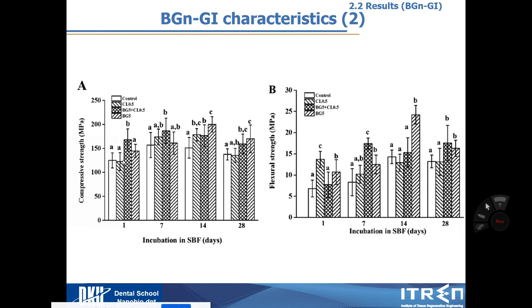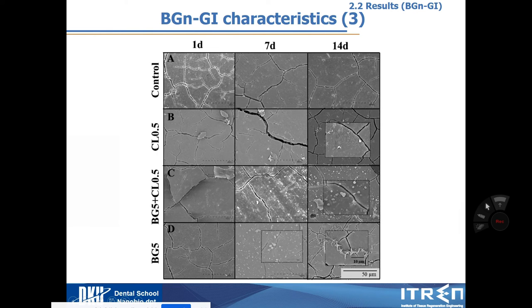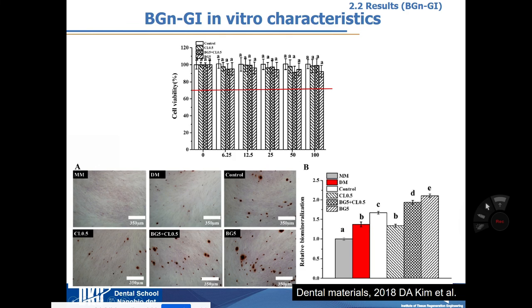And then I check their strength. Strength is also checked over 28 days incubation in body fluid. It is more similar between BGN 5% and control, or a little bit increased here. And then I check their bioactivity. When this glass ionomer incorporates BGN 5%, it starts to show hydroxyapatite formation, which is a good sign for dentin regeneration. And then I check the viability, which is similar, but the regeneration ability is highly increased in BGN 5% included, which is quantified by ARS staining.